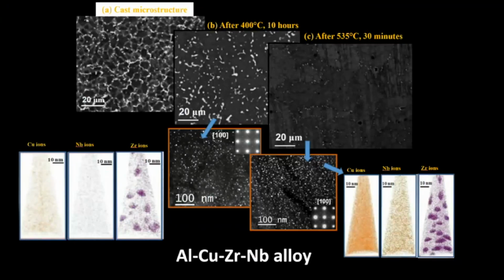This is the microstructure. As you can see on the left, it is the cast microstructure, and after 400 degrees centigrade 10 hours, a lot of segregate disappears even at this temperature. But if you do a TEM, you can see that the matrix is full of L12 precipitate, L12 that you can see from the inset diffraction pattern. We have also confirmed it by APT, and you can see the nice precipitate of L12 comes out. After this, we upquench to 535 degrees centigrade.